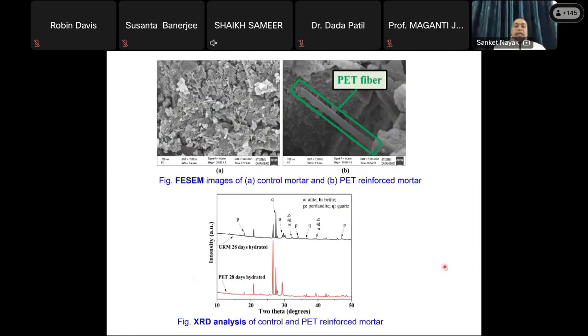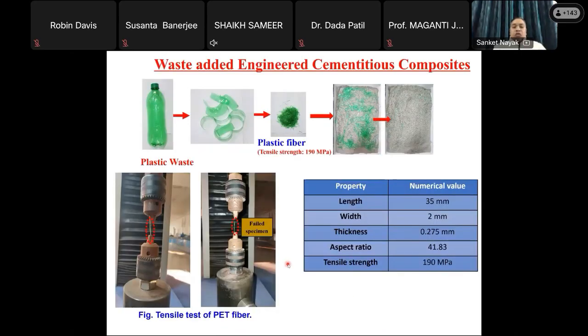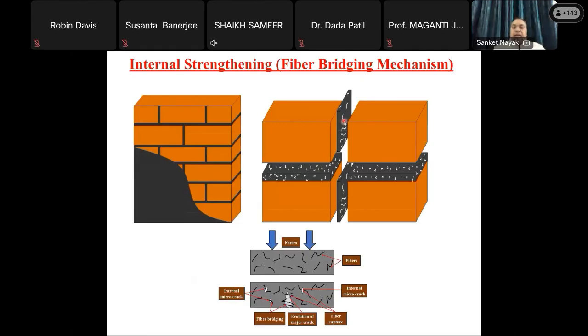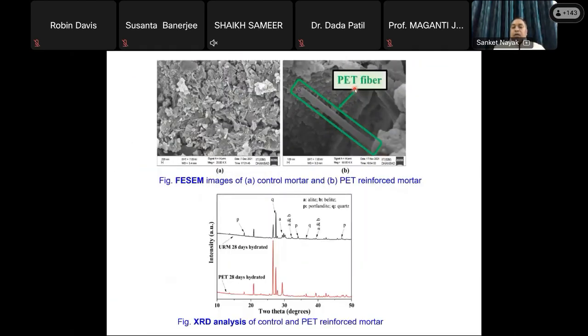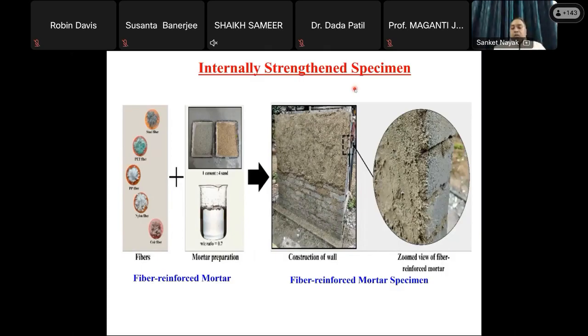Once this mortar is formed, we have to see what the mechanism is, what the microstructural analysis is. So this is the microstructural analysis, the FESEM and XRD analysis of the PET fiber with respect to the unreinforced one. Similarly, we have carried out analysis for the others, to know what mechanism is followed, so that this technique is effective and the fiber bridging action contributes towards the overall stability or overall improvement of the structural behavior.